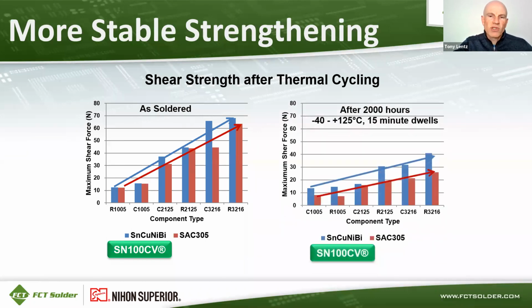And then after thermal cycling was done, 2000 hours, -40 to +125 C, you can see the overall shear force drops off for both solder types, but the SN100CV still outperforms the SAC 305 shear force.